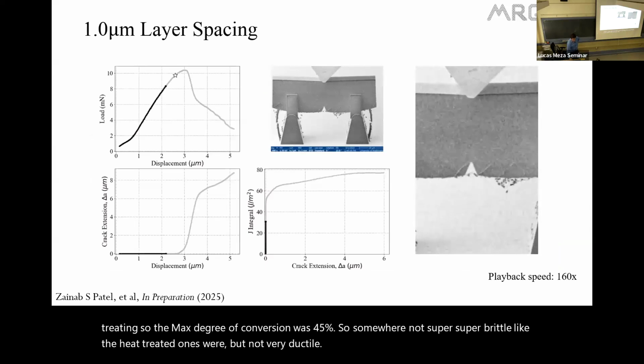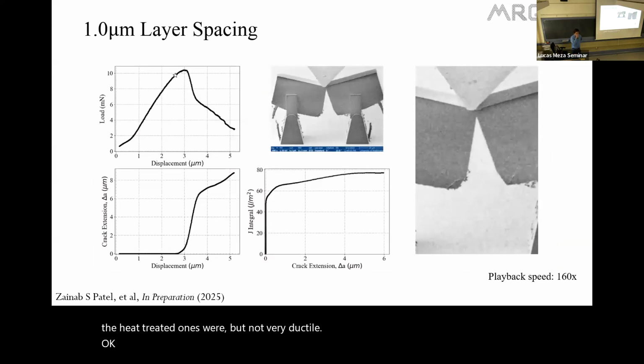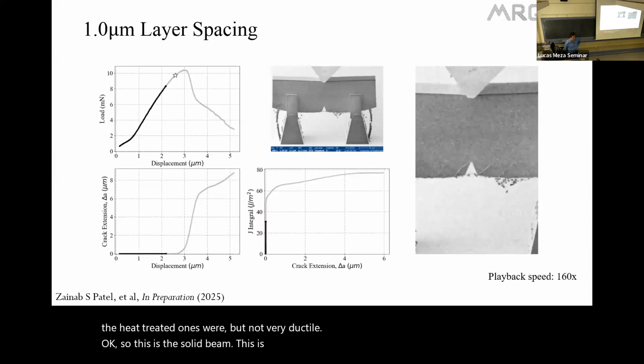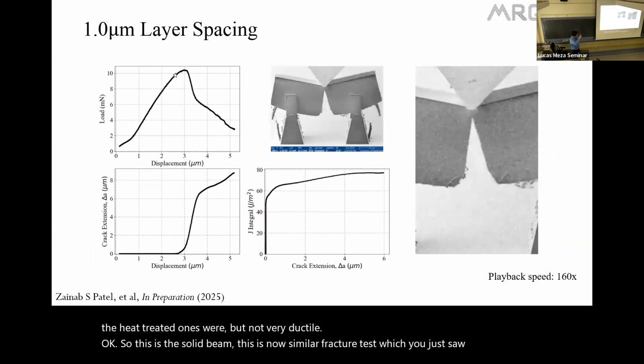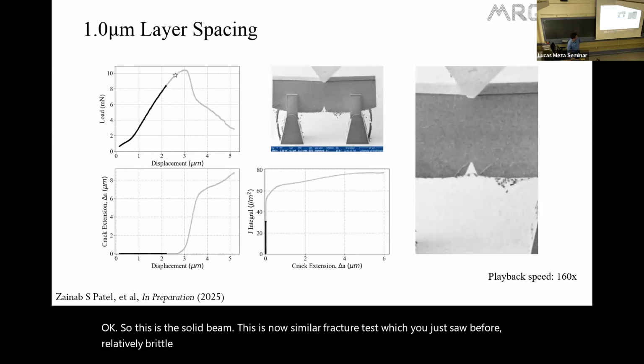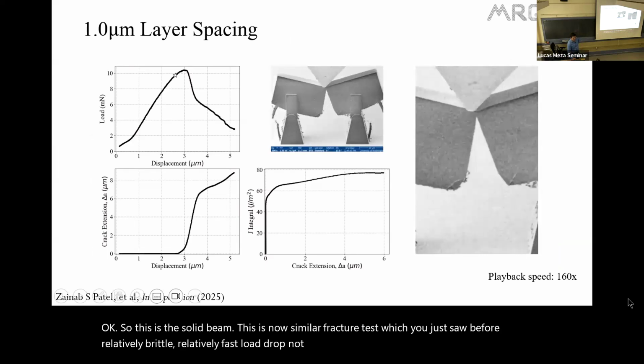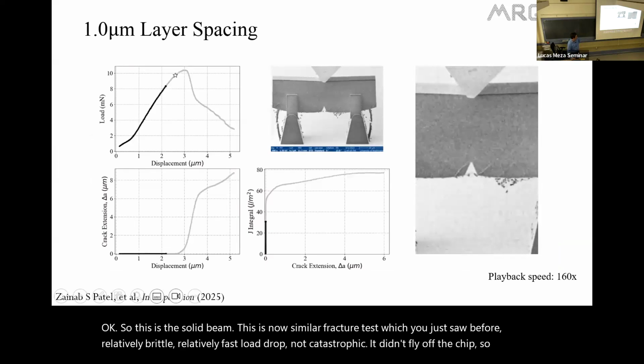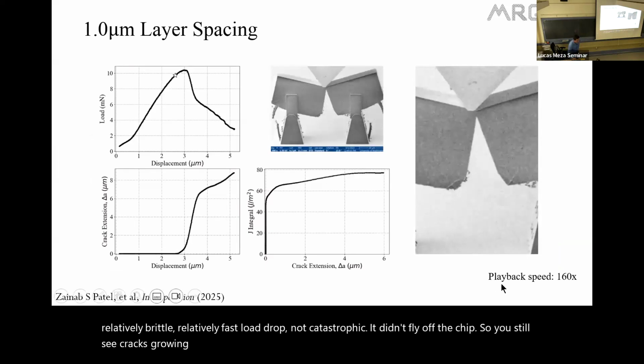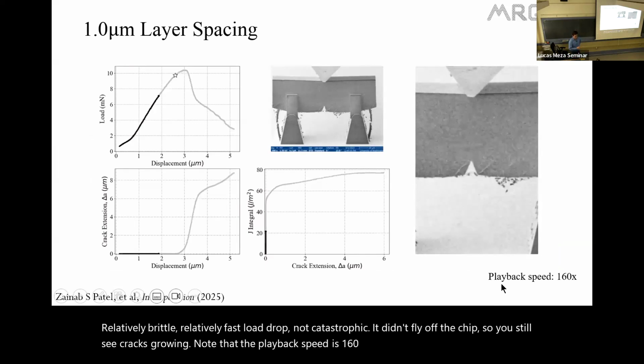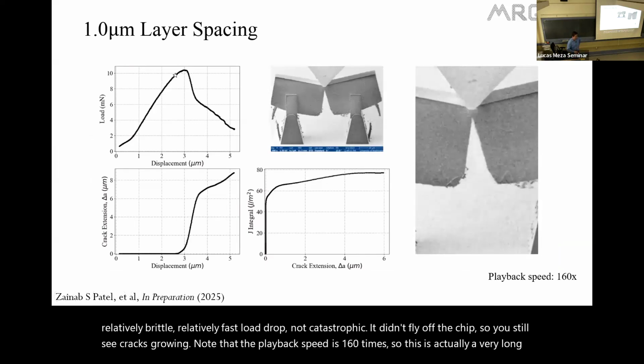Okay, so this is the solid beam. This is now a similar fracture test to what you just saw before. Relatively brittle, relatively fast load drop, not catastrophic. It didn't fly off the chip, so you still see cracks growing. Note that the playback speed is 160 times. So this is actually a very long slow test. It takes like 10 minutes to do, but sped up here.